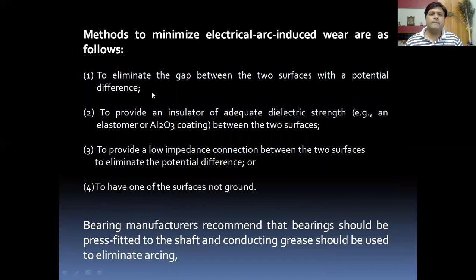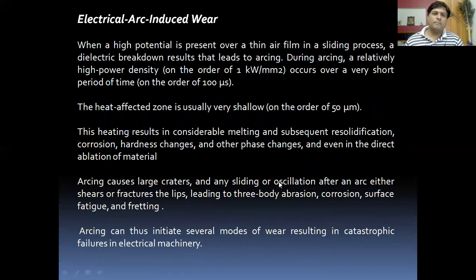Now, there are methods to minimize arc-induced wear by eliminating the gap between the two surfaces to reduce the potential difference, or by providing an insulator of adequate electric strength between the two surfaces, or by providing a low impedance connection between the two surfaces to eliminate the potential difference, or by having one of the surfaces not grounded so that there is no dielectric breakdown.